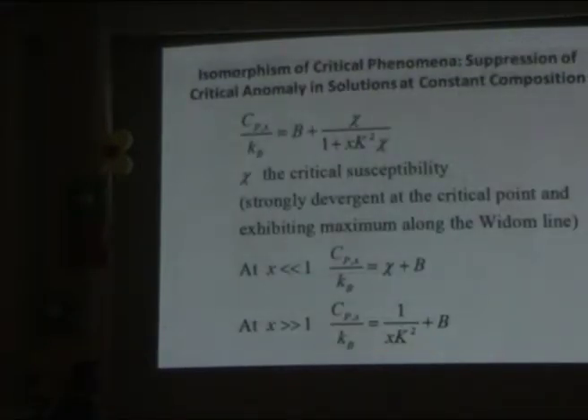Okay, next slide. So basically, it is a couple of slides and I'm finishing. The heat capacity in solutions is described by the so-called crossover formula. There's a background of the heat capacity. There's a strong susceptibility, or you can say heat capacity in pure water. This is the Krichevskii parameter and concentration. That's all. When we are far away from the critical point, susceptibility is small, or concentration is small, or the Krichevskii parameter is accidentally very small, the heat capacity in solutions will behave similar to pure water.